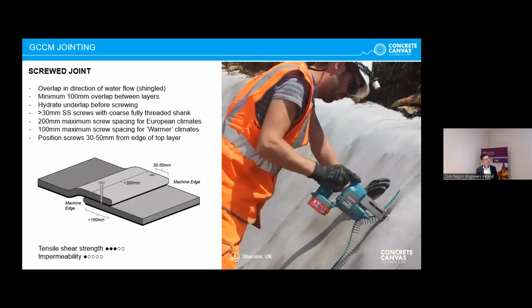The second installation principle is securing the material together. Typically, what we recommend is overlapping the layers by 100 millimeters, shingled the overlapping layers in the direction of water flow, as you can see in the cross section on the left-hand side, and to mechanically fix the joints together at 200 millimeter centers with 30 millimeter stainless steel screws. So this gives you a high mechanical strength joint, but at the same time, it allows for, if there's a high water table, any water from underneath to drain out through your joints and prevent any hydrostatic uplift pressure. So that is a really good joint detail.